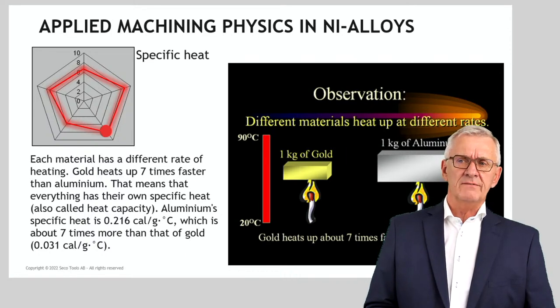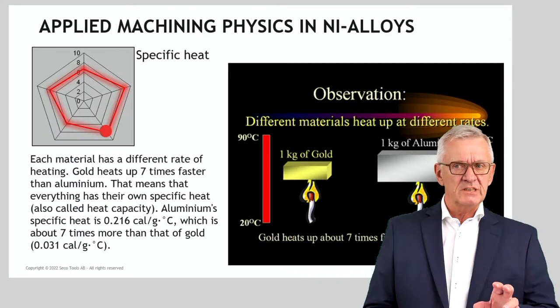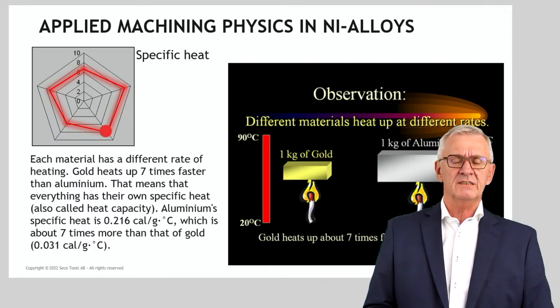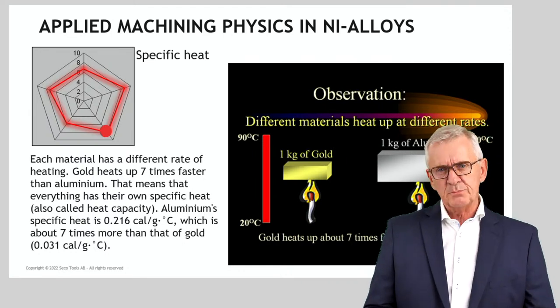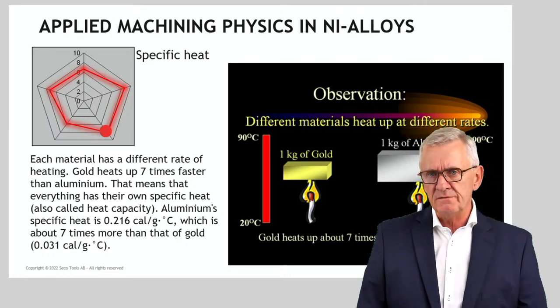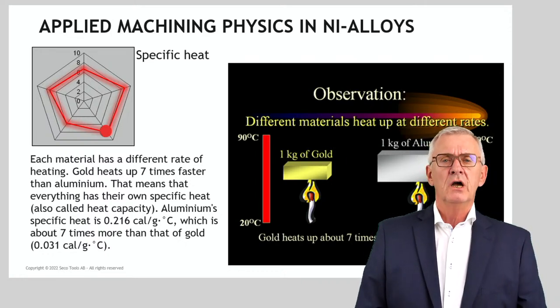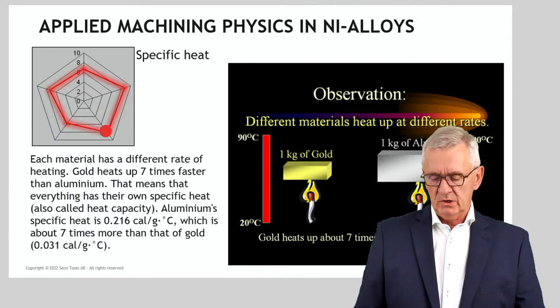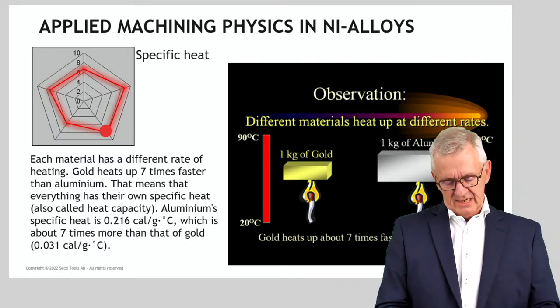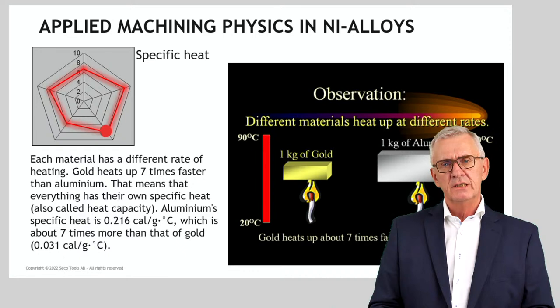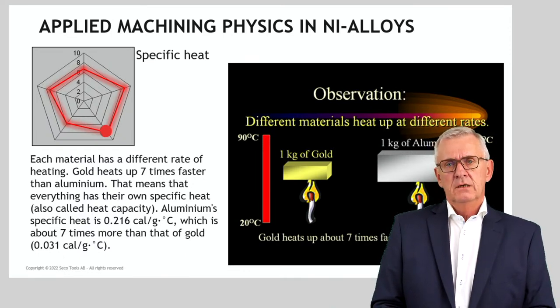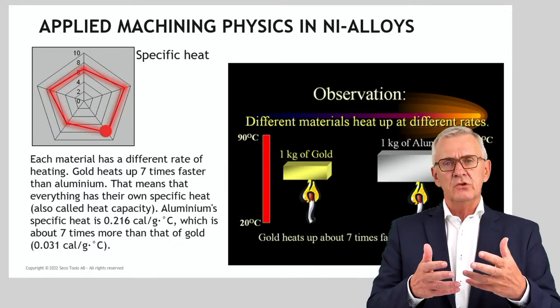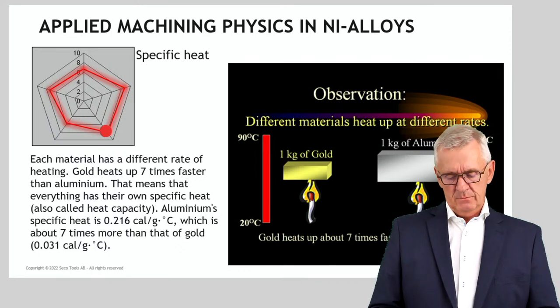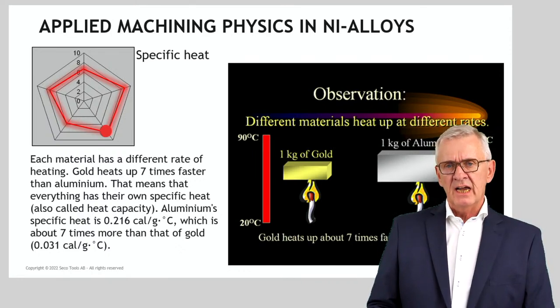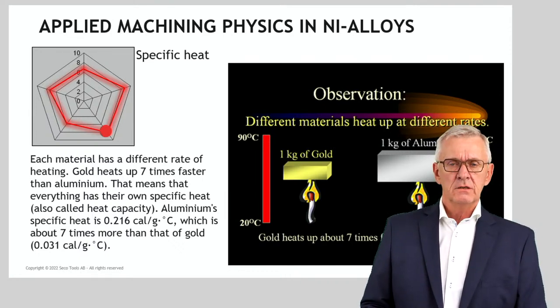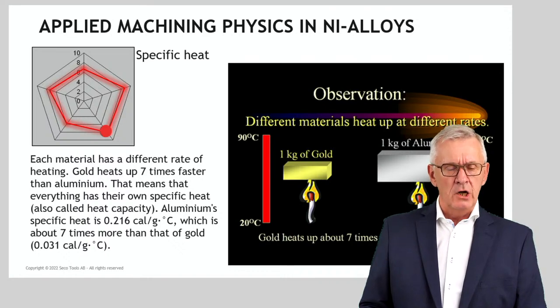Now, talking about this, I also have a little footnote with specific heat. It's not in the diagram, it's not in this pentagram, but specific heat is also something which is rather important when we machine nickel-based alloys. First, what is specific heat? Specific heat is the amount of energy you need to increase the temperature of something by 1 degree. Because metals, if you want to increase them from 20 degrees up to 21 degrees, need a certain amount of heat to do that. And when the volume you talk about is the reference volume, the heat you need, we call the specific heat. But if the material is already 800 degrees and you want to increase it to 801 degrees, that demands a lot more heat, a lot more energy.